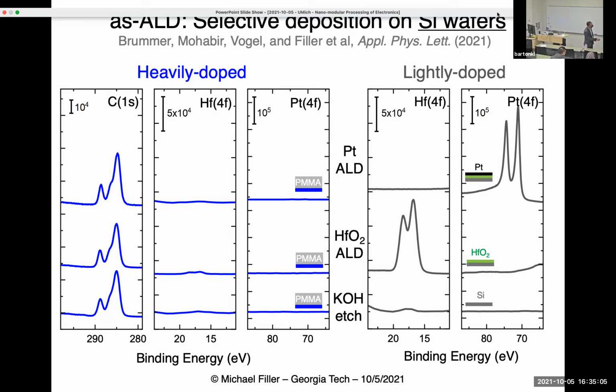On the right-hand side, the lightly doped side, we removed the PMMA. We no longer see the carbon here, but we have nothing on the surface, basically bare silicon, and then we add hafnia, which is what we want, and then we add platinum, which is what we want. So on the lightly doped region where we're able to remove the PMMA, we can get both hafnia and then platinum to go down.